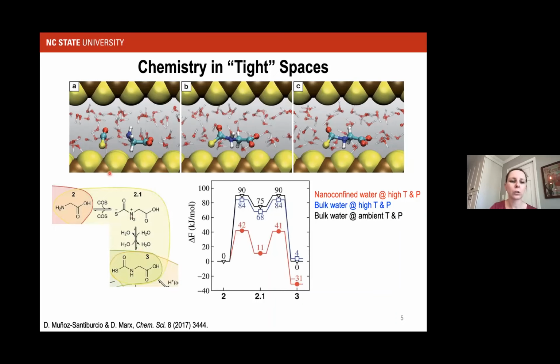And this particular panel shows this organic reaction here. And here they show the free energy change as a function of the reaction progress if you consider the situation under nano confinement at high temperatures versus if the same reaction was occurring in bulk water at high temperatures in blue or at ambient temperatures in black. As you can see very clearly is that under confinement, that free energy change, that energy penalty is essentially minimized, making these reactions happen much more easily. And I thought this was really fascinating because essentially the material here, the iron sulfide, was providing this confinement template and driving or making this reaction much more favorable. And later on in this paper, I believe they even say that reactions like this could be how some of the early complex organic molecules were made, in the beginning of time, if you will.